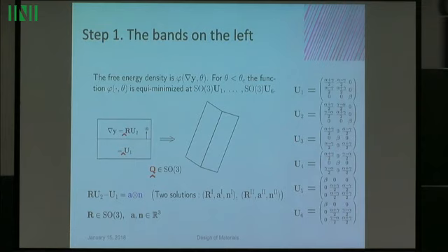And the condition of compatibility assures the picture does look like this and not two separate blocks. This condition is an algebraic condition. U2 and U1 are given. R is a free rotation matrix. Algebraic problem: find R such that RU2 minus U1 is a rank 1 tensor, a tensor N. If you do that, that's not hard to do. And there's two explicit solutions. You write down everything about those three quantities. If you come back up here and compare with this one, if you've chosen the variants correctly, you'll accurately produce this picture, even at the atomic level.